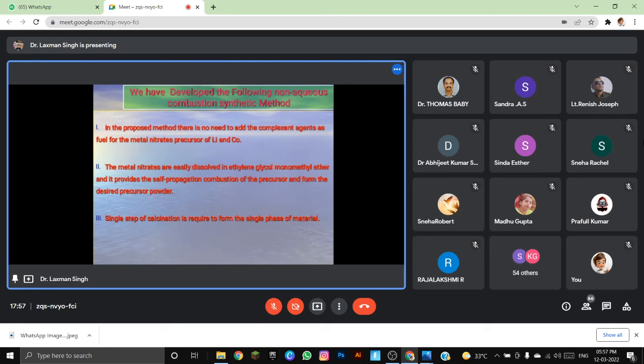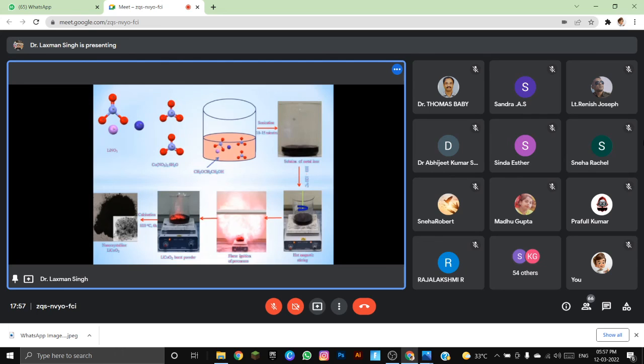Within 55 minutes to 1 hour, we can get the nanoparticles. We just take lithium nitrate and cobalt nitrate, mix them in 2-methoxyethanol, and sonicate for 10 to 15 minutes. Then it gives a clear brown solution. Then just heat it up on a hot magnetic stirrer. It will take 30 to 45 minutes.